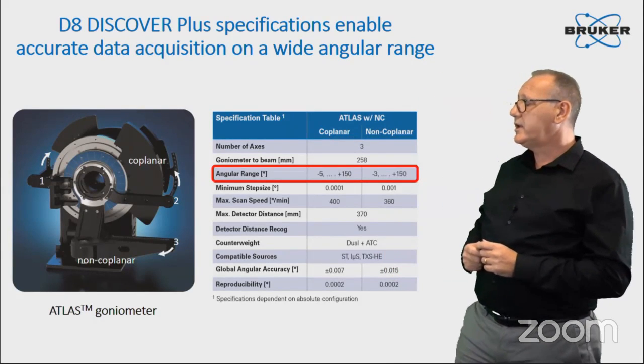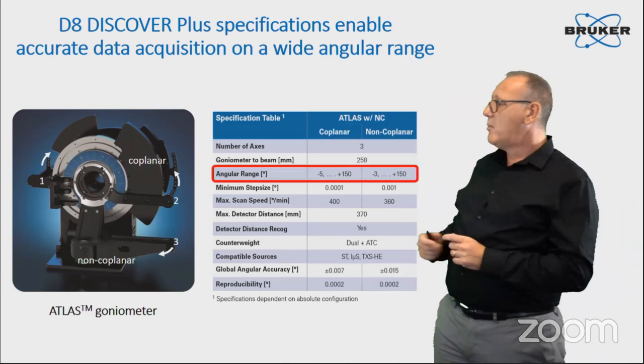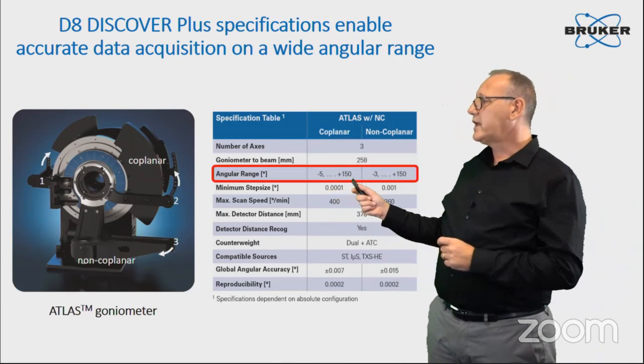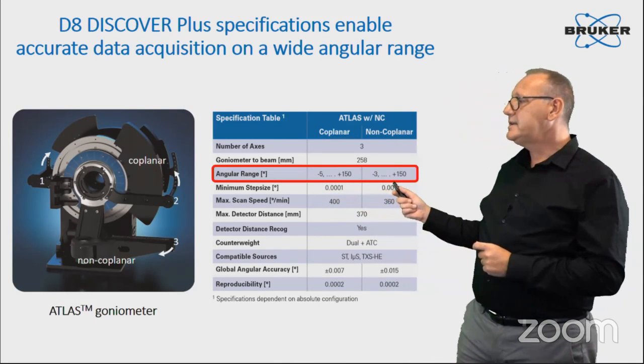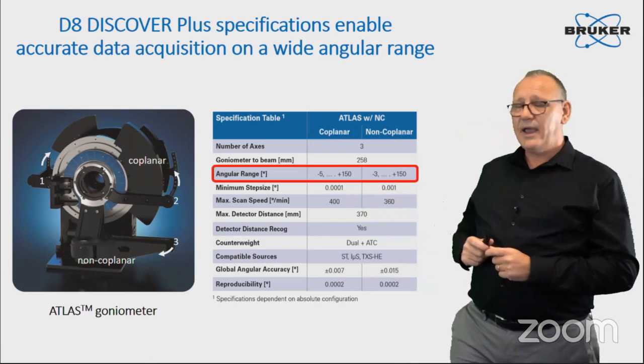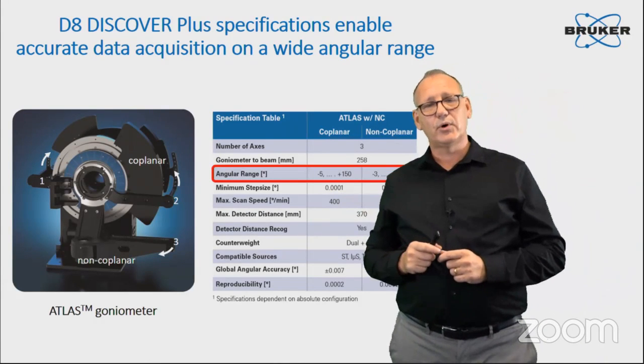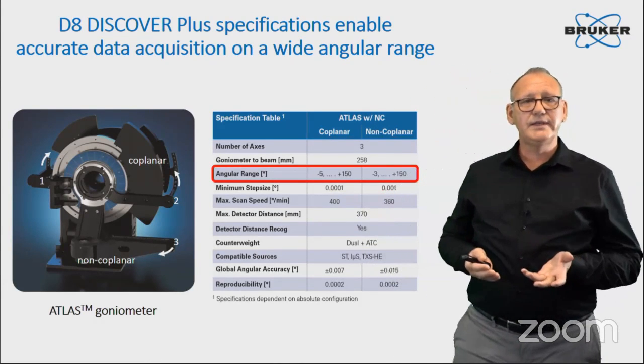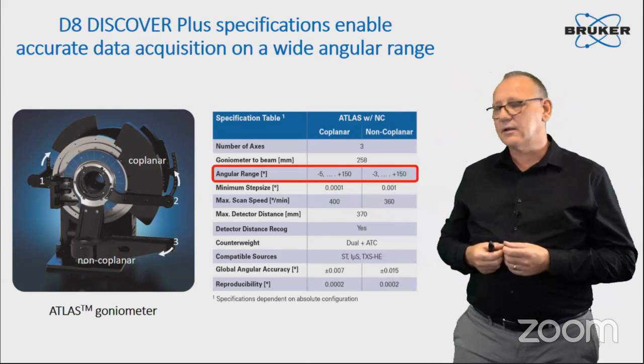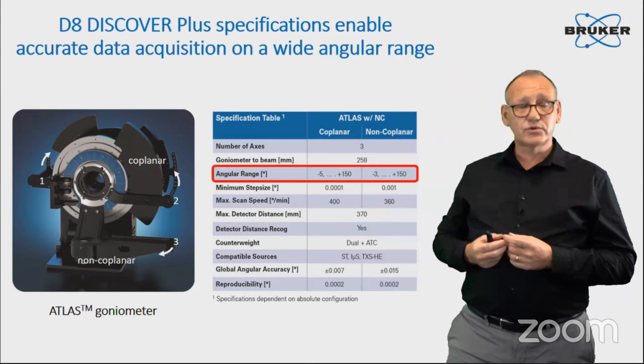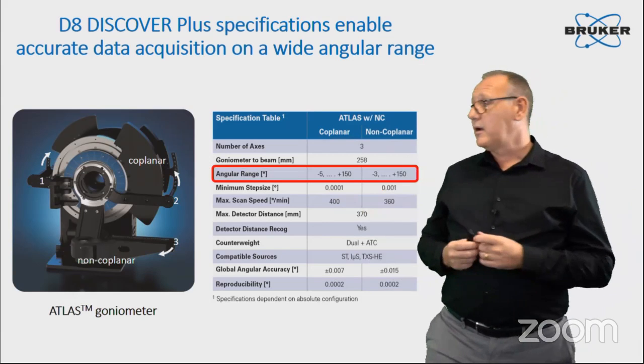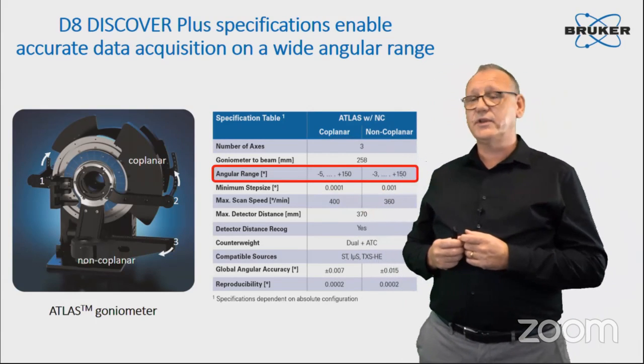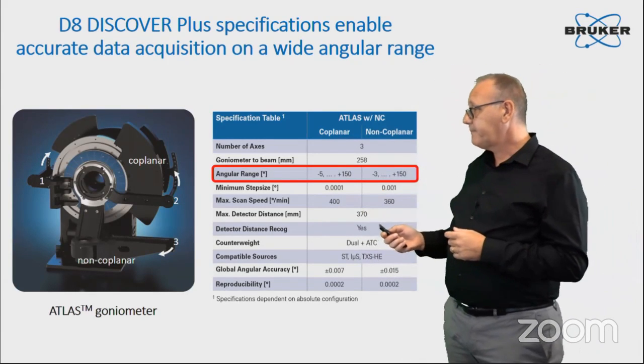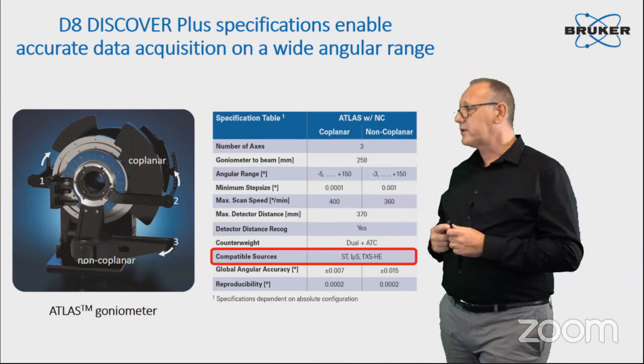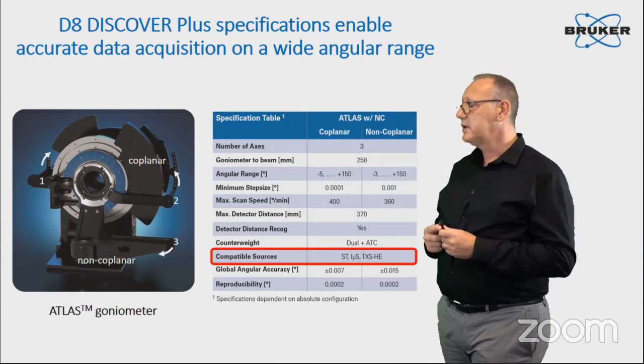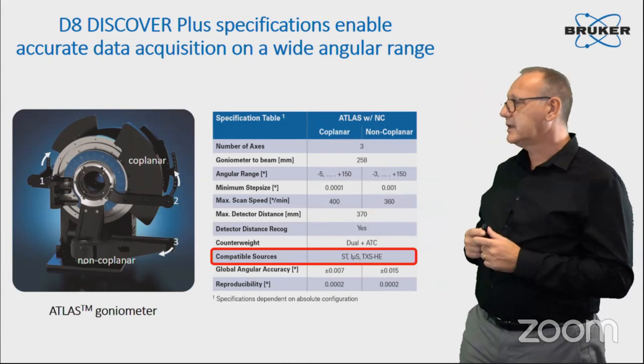What is remarkable on this goniometer is the scanning range of both axes. Both could be up to 150 degrees. And we will see later that the high angle data can be extremely important to either increase the accuracy of your result, but also can be crucial to observe some sample effect on the diffractogram. You can equip the diffractometer with different types of source. This we will review a little bit in the next slide.